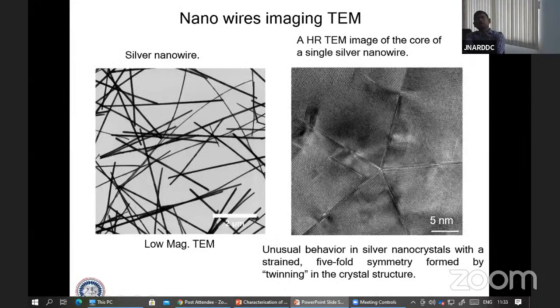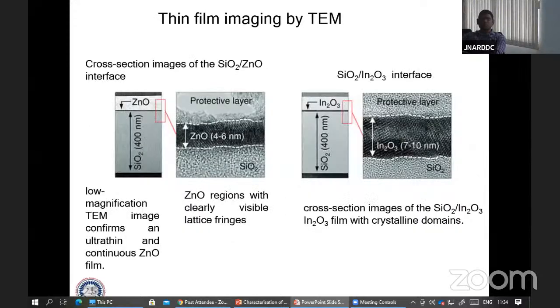Suppose you have a nanowire. So low magnification TEM is showing, in the left side image, a silver nanowire. And you can also see a high resolution transmission electron microscope image of the core of a single silver nanowire. So this also has a 5-fold symmetry, where within that we can see some twins, twinning in nature. So this can also be possible under a transmission electron microscope. We can also see the atoms clearly by using some software. And in the cross-sectional images of the silica and the ZnO interfaces, you can see the ZnO thickness.